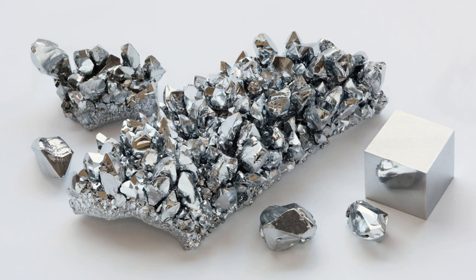layer of chromium oxide. Still, this oxide layer that was found on the weapons was not pure chromium metal or chrome plating as it is commonly produced today, but a mere 10 to 15 micrometers layer of chromium oxide molecules at up to 2% chromium was discovered, which turned out to be enough to protect the bronze from corroding.